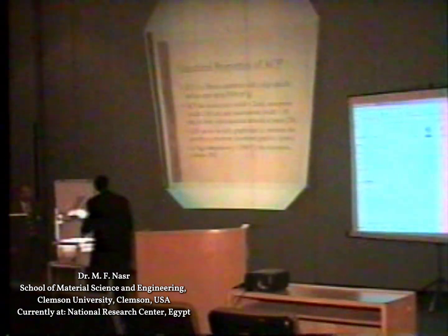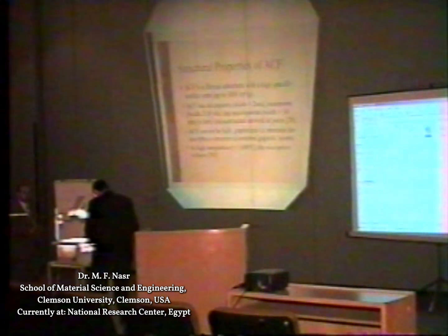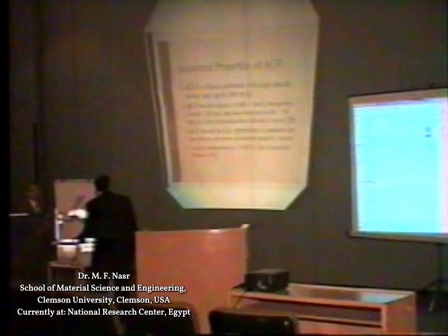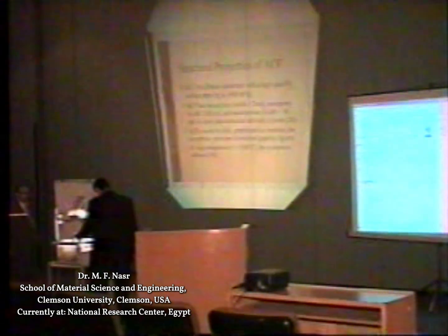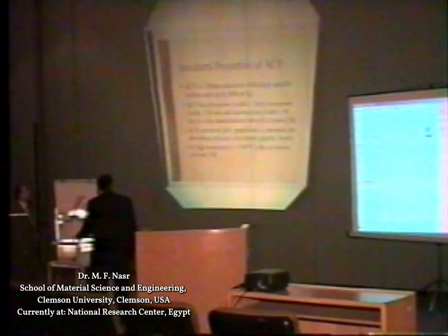The activation step changes, like I said, the surface structure of the carbon fiber and transforms it to the activated carbon fiber. The activation creates a huge surface area, and it can reach up to 3,000 meters squared per gram of the fiber, which is huge, of course, and this is the importance of the activated carbon fiber.